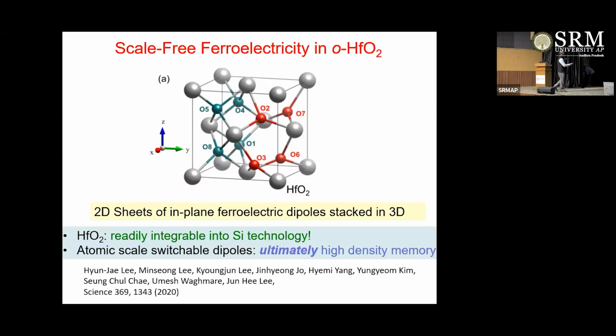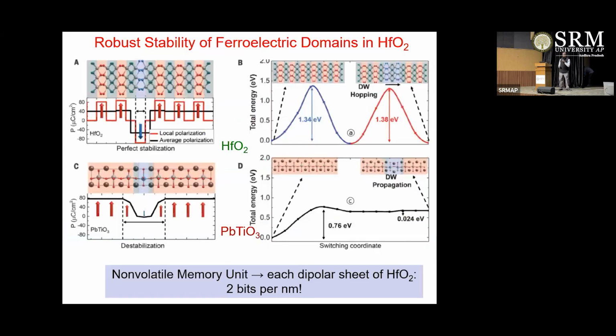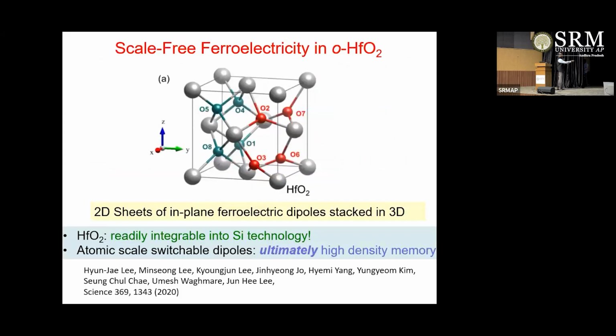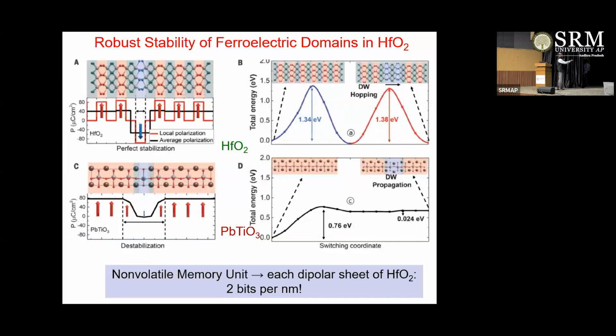And this is basically the hafnium oxide. It's a crystal made up of hafnium and oxygen atoms. And what we showed in this work is very fascinating. So hafnium oxide, as you see, has oxygen atoms and hafnium atoms. And you can switch one plane of oxygen atoms to up or down direction the way you want, and it still is a very stable crystal. So it's a crystal which allows us to control its local structure at atomic scale using external electric field.